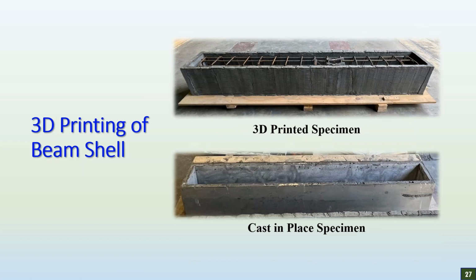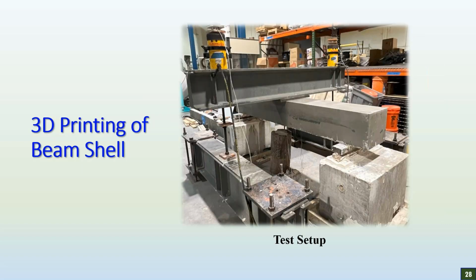Now, to see the behavior of this printed specimen, a similar cast in place specimen was also constructed, which is shown at the bottom here. In both of these specimens, the reinforcement cage was placed inside them and filled with normal concrete. A third specimen with the same dimensions and same reinforcement ratio with regular concrete was also prepared, and all were tested for 3-point loading in the lab. This is the loading setup. As you can see here, the beam is placed, and the hydraulic rams were used to apply the load on top of the beam, and the beam had a simple support with an effective span length of 7.5 feet.